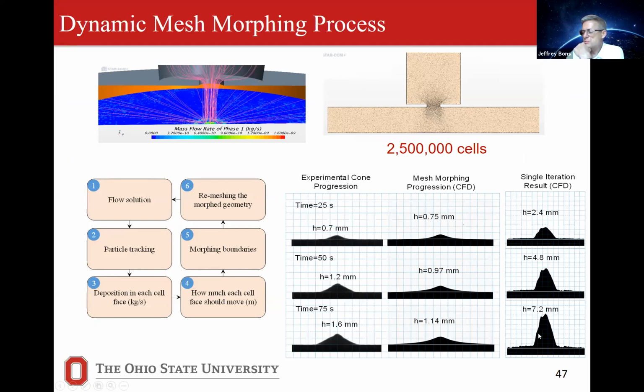And I'll just point out that this is what you get if you don't account for what's called mesh morphing. So as a surface accumulates a deposit, it has a first order effect on the flow field. And you have to account for that by adapting the grid. And if you don't adapt the grid, look how tall these cones are. So the prediction would tell you that you get 7 times or 6 times the height of that cone compared to what's seen experimentally, 1.6 millimeters, if you don't account for mesh morphing. So we're getting higher and higher fidelity in our simulations. So this is a very active area for us. We have government as well as industry funding, and we're probably looking for at least another student in the fall to be involved in that work.